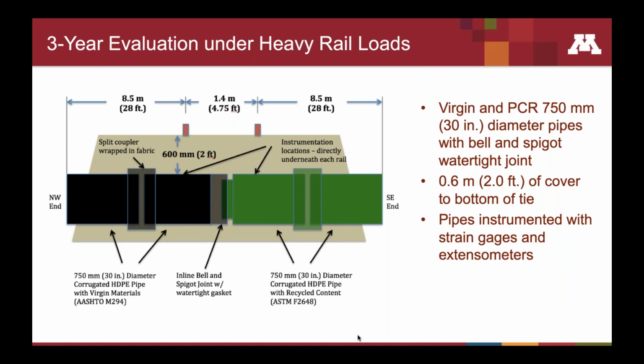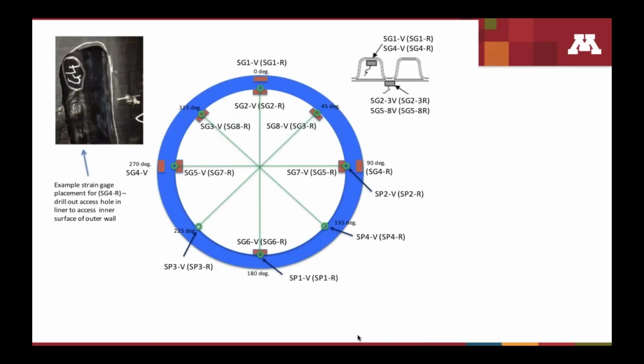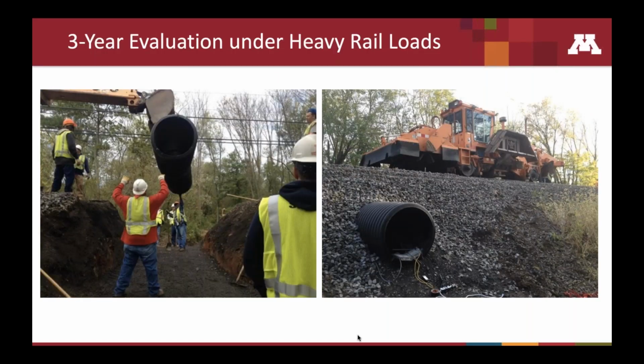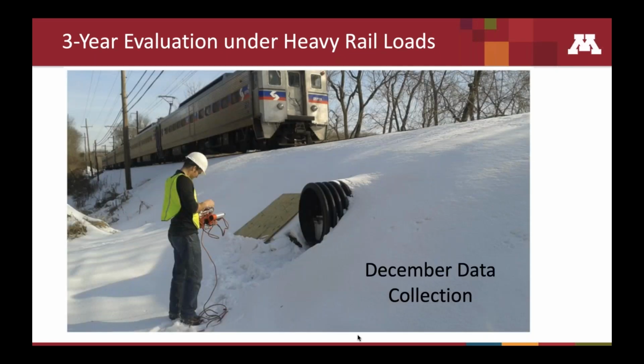And the pipe on the left, the black one, is manufactured with virgin materials, and the pipe on the right is manufactured with recycled materials. And we coupled them end to end so that both pipes were seeing the same exact load from the railroad cars. We instrumented these pipes with strain gauges as well as string potentiometers to record deflections and strains in the pipe wall. We shut down the track for a day to do a complete installation. And then we monitored the loads in the pipes over time to see how they performed.